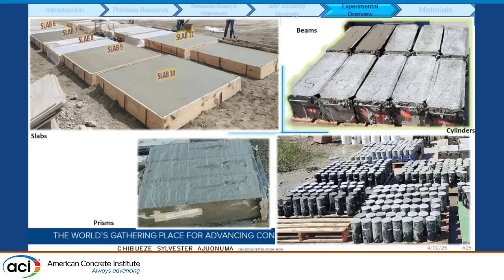And then we also had some beams. We were able to cast 12 beams of 6 by 6 by 18 inches for flexural testing, and then also some prismatic samples for drying shrinkage. We also had some cylinders which we cast in the field, but transported back to the laboratory so that we could test them in the lab.